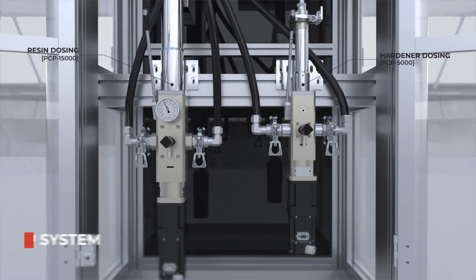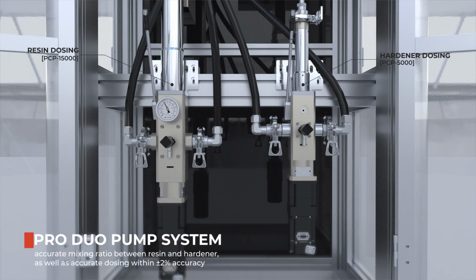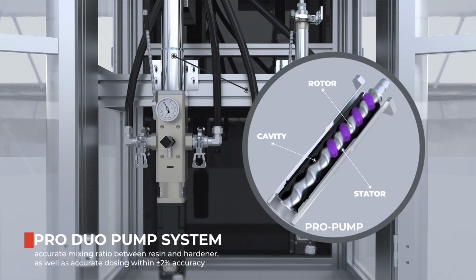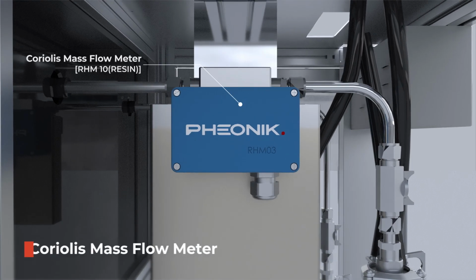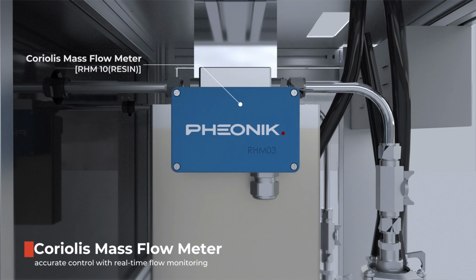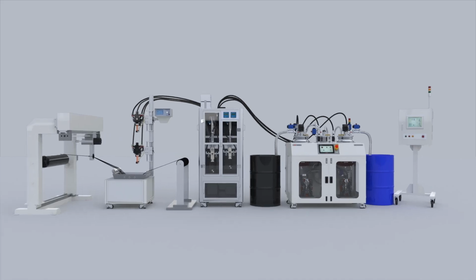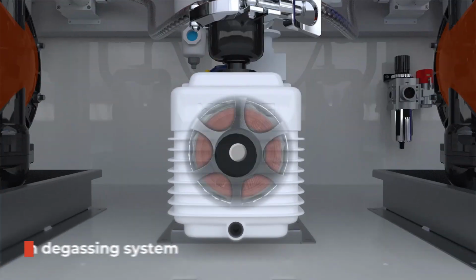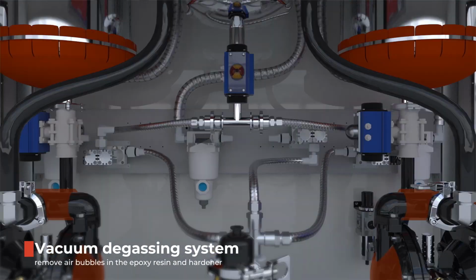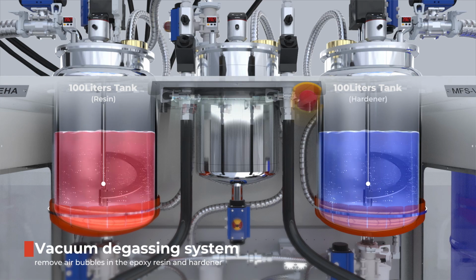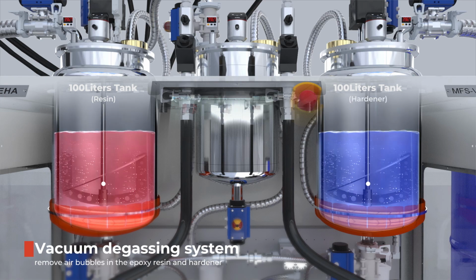The Pro Duo pump system maintains the accurate mixing ratio between resin and hardener, as well as accurate dosing within plus or minus 2% accuracy. A Coriolis mass flow meter is adopted to monitor and support accurate control with real-time flow monitoring. A vacuum degassing system is adopted to remove air bubbles in the epoxy resin and hardener to ensure the impregnation process.